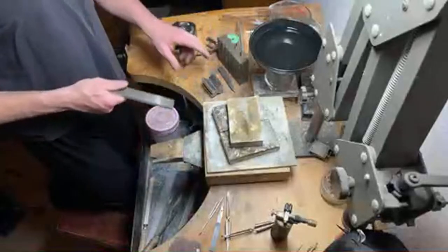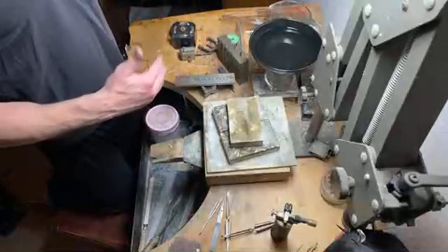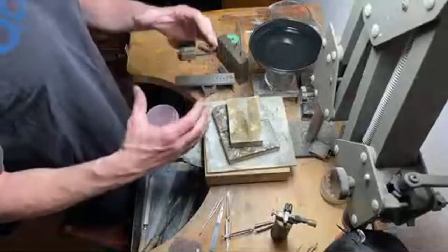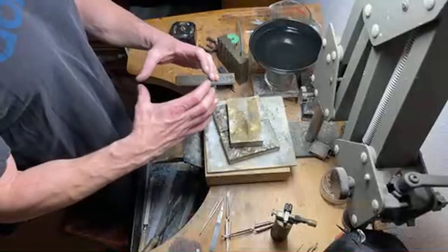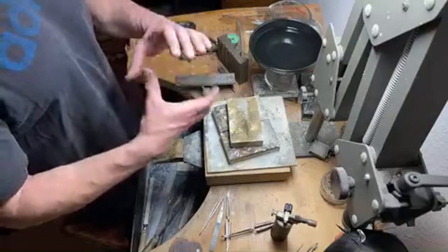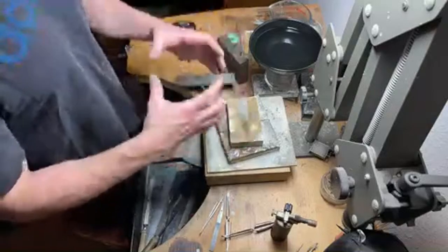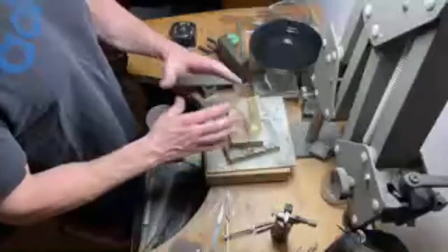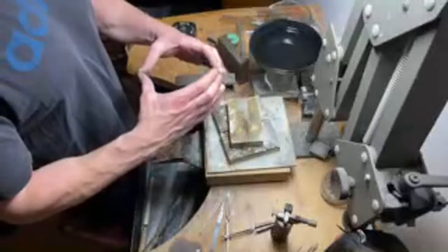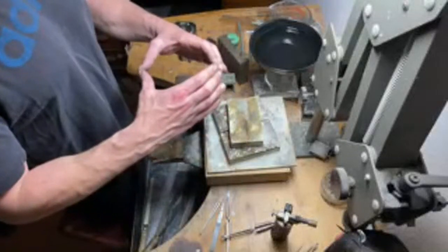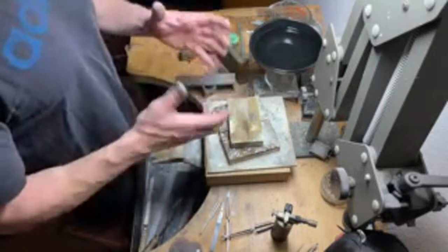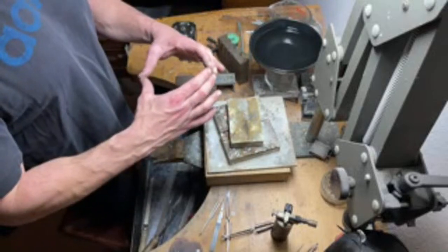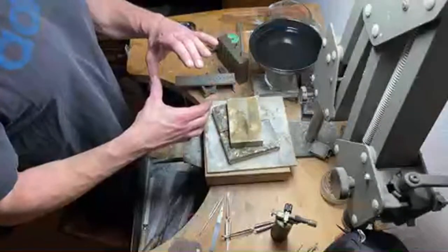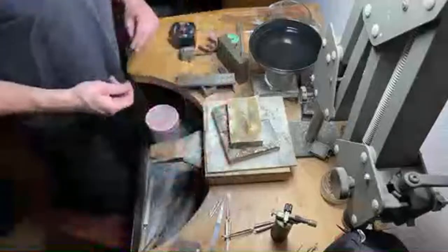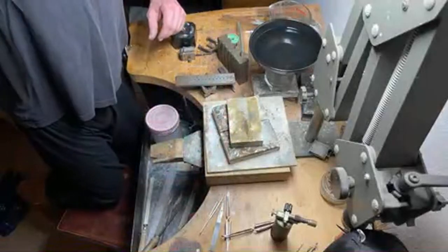and once they're at the right size, they then need annealing again before we manufacture. Otherwise, if we don't anneal it before we start forming the rings, when you go to solder them, the wire anneals, and as you can see, when it relaxes, it moves. So if you don't anneal it before the soldering process, it anneals before the solder flows, and what tends to happen is the metal relaxes. You end up having to do it twice.